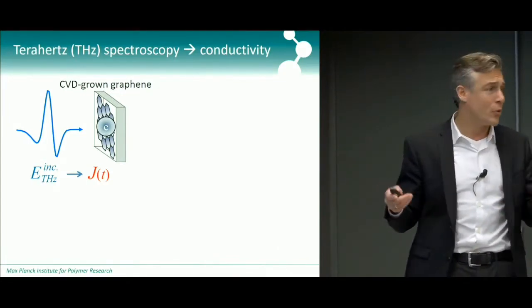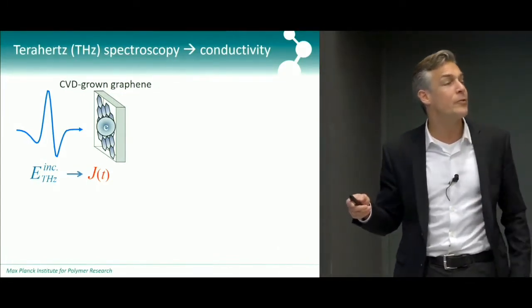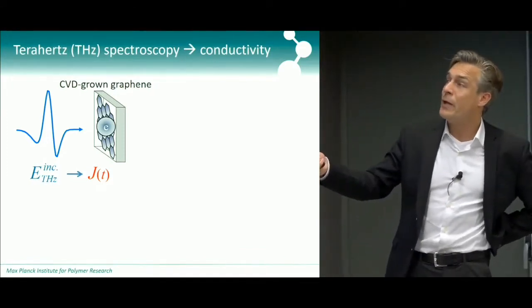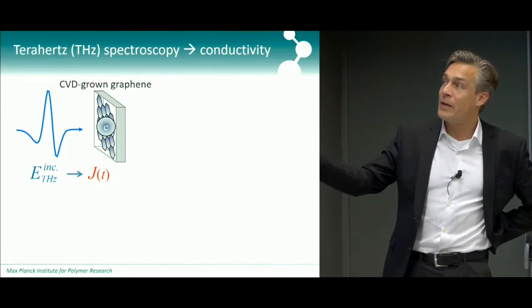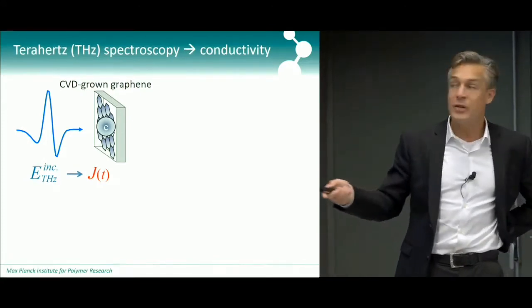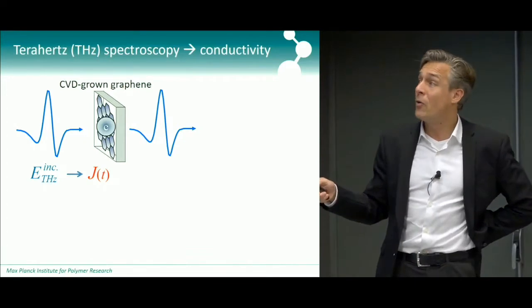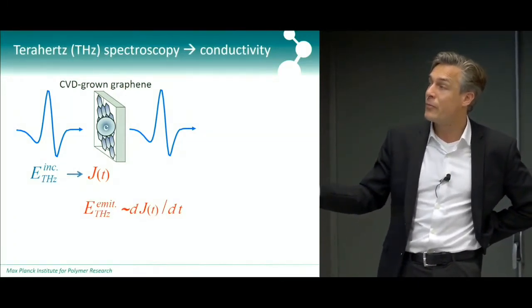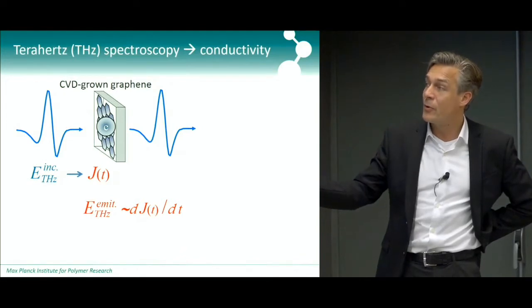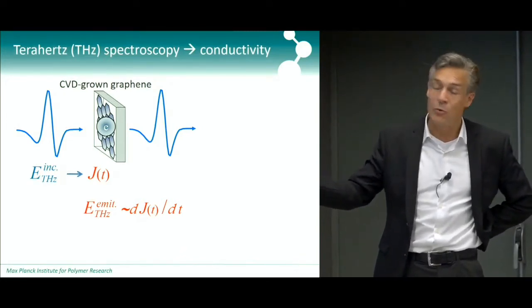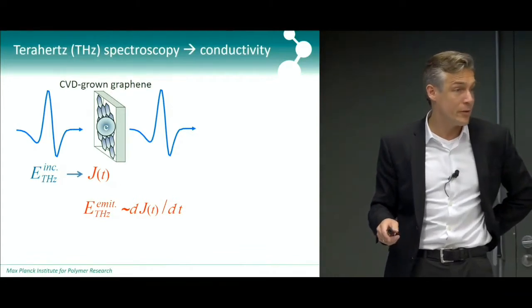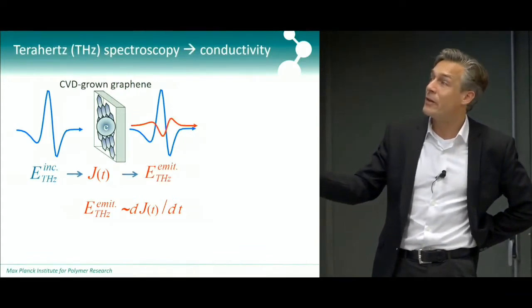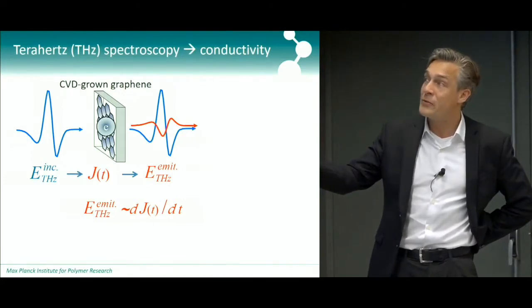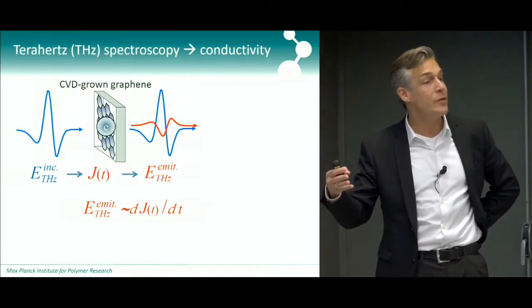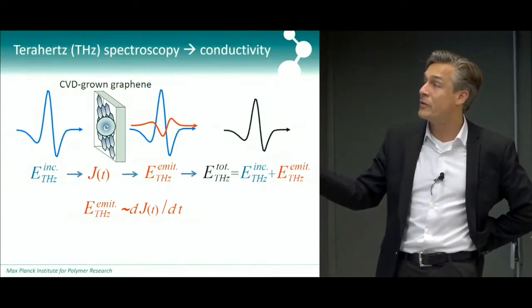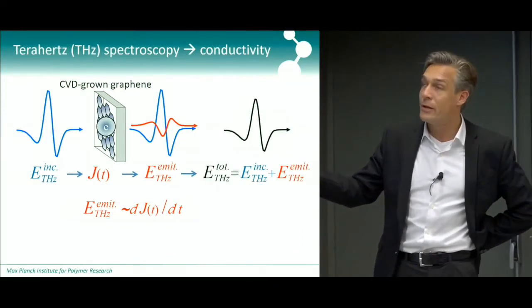So how does that work actually? And this is important for the rest of my talk. It's actually very simple. The incoming terahertz pulse, by accelerating those charges in graphene, generates a current. Now, you all know from your electromagnetism class that a current will emit a field, and that emitted field is proportional to the time derivative of that current. And so what happens is that this current is out of phase with the driving field, and that gives rise to essentially interference and a reduction in the terahertz pulse.